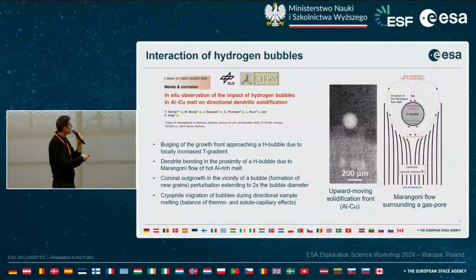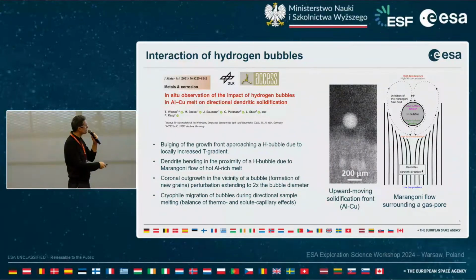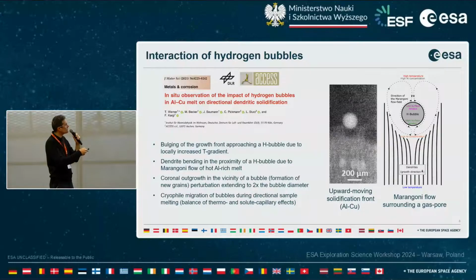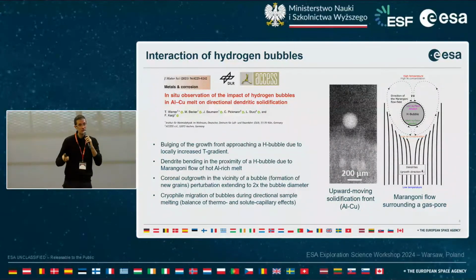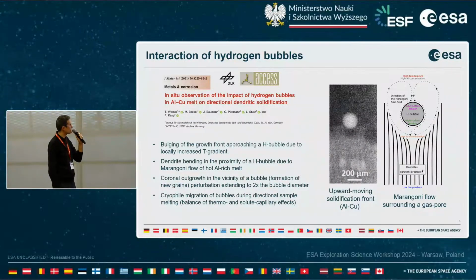And also, what I find very interesting is a cryophile migration of bubble during directional solidification, because what we expect when you have such a dihydrogen bubble in temperature gradient, you expect the bubble to move up towards the hot zone. But what was observed is the contrary effect. The bubble has been migrating towards the cold zone, and this, after interpretation, illustrated the fact that both thermal effects and solutal effects have to be considered in order to describe Marangoni flow. And this, depending on the conditions, explained the fact that the bubble has been migrating toward the cold zone instead of the hot zone as usually observed.